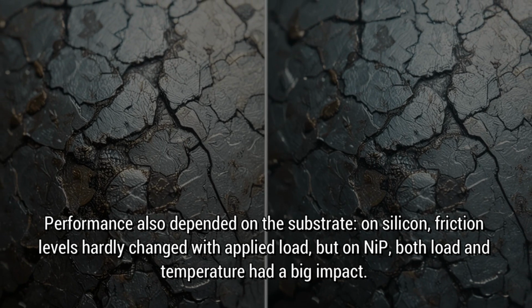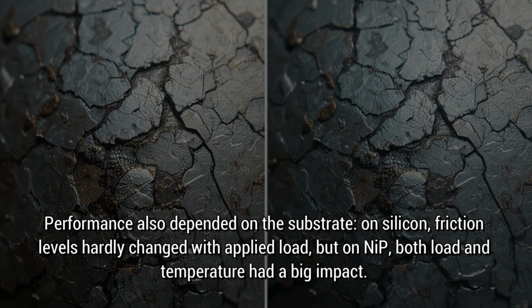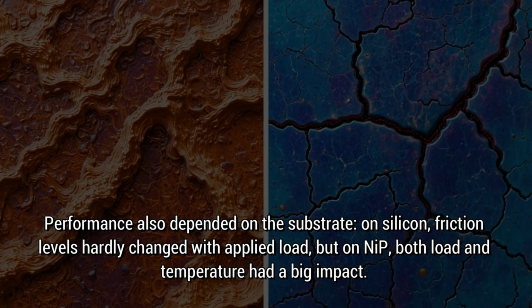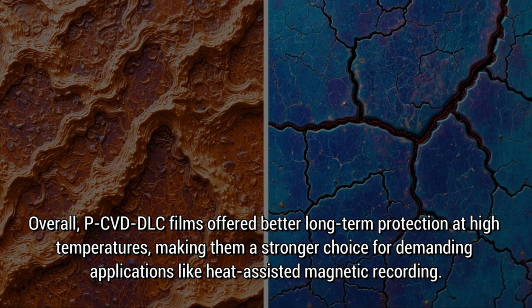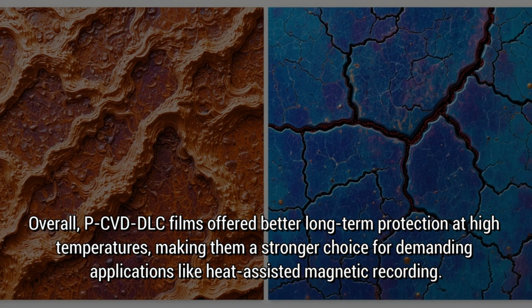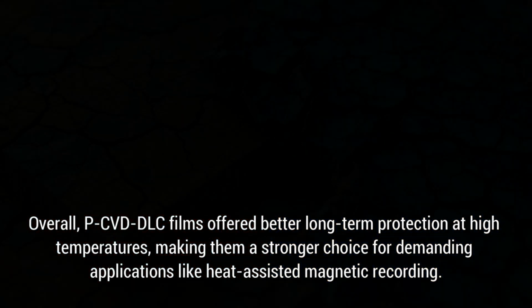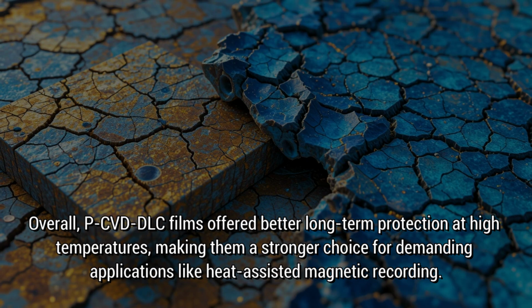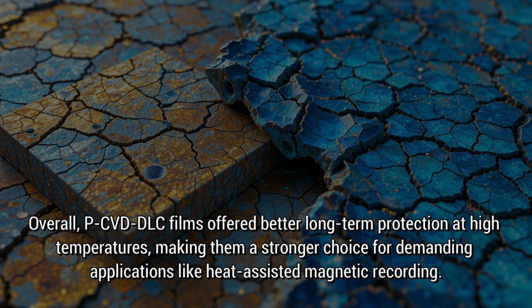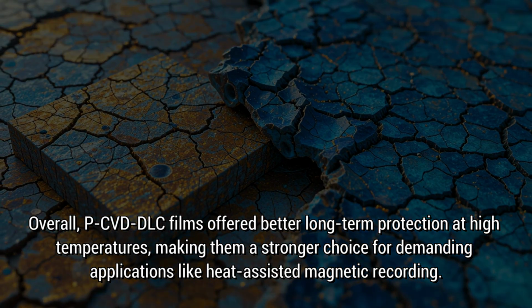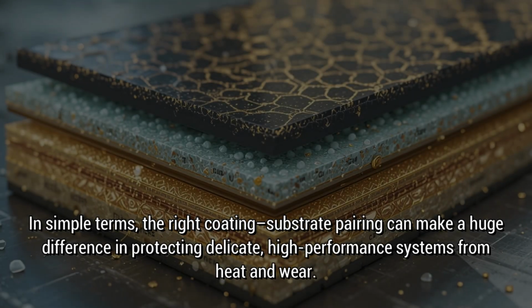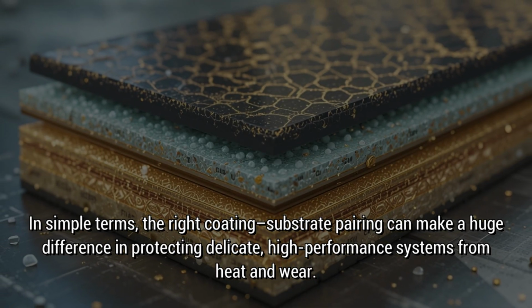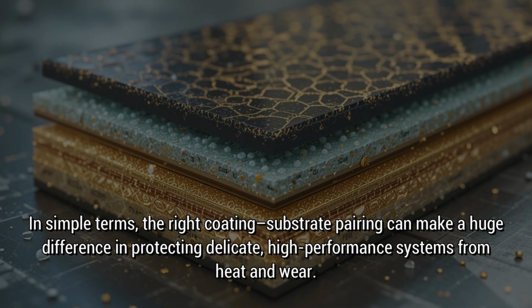On silicon, friction levels hardly changed with applied load, but on NiP, both load and temperature had a big impact. Overall, P-CVD DLC films offered better long-term protection at high temperatures, making them a stronger choice for demanding applications like heat-assisted magnetic recording. In simple terms, the right coating-substrate pairing can make a huge difference in protecting delicate, high-performance systems from heat and wear.